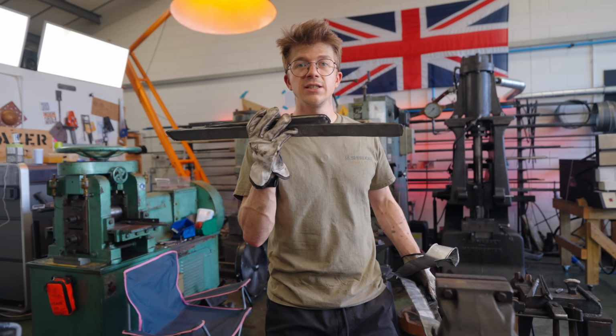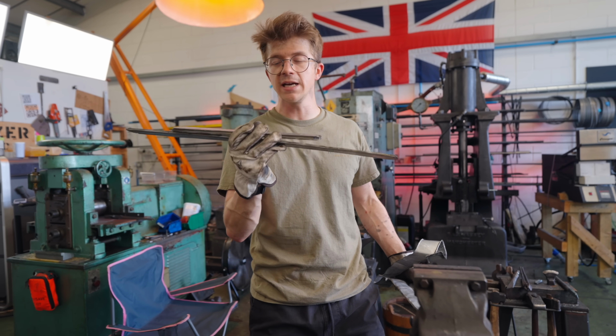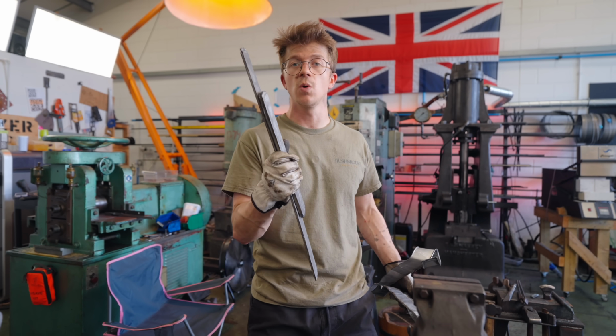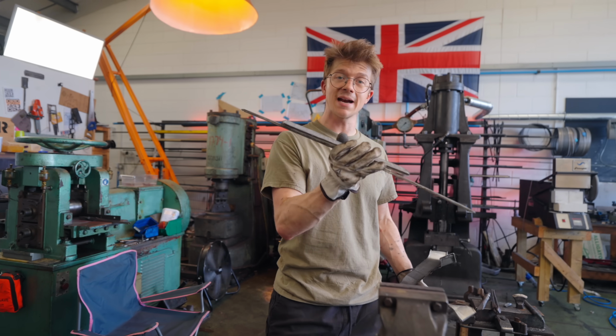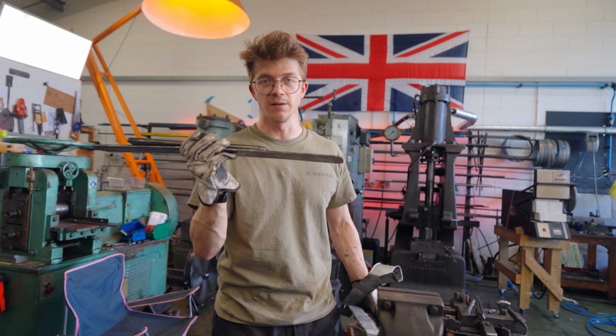And so the reason that I chose to not go for a direct bond but go for the nickel interlayer is so that we have the ability to do what we're about to do, which is heat them back up and forge them out to final dimension.